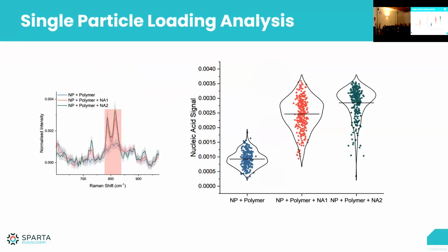And we can also use that to look at some loading analysis. So for instance, here we can see that we have a different ratio of particles showing nucleic acid signal and a different amount of nucleic acid spread across these particles. So this is all stuff that we can analyze. And we can actually see that the amount of loading, which you can calculate in the software, is different on an average perspective.